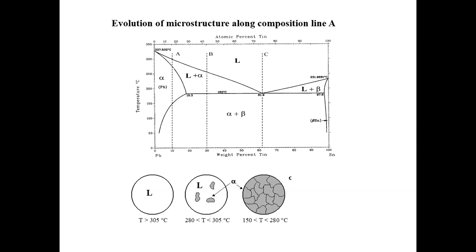Okay. So now before I show the last picture, we know that if I further cool the system, what phase are you going to have if I further cool the system down here? So alpha plus beta. You're going to have alpha plus beta. Does this make sense to everyone? Because I'm now in the two-phase coexistence region. Now, if I just choose this like 100 degrees Celsius, give me a rough estimate. What are going to be the corresponding equilibrium compositions of alpha phase and beta phase? Approximately those. Beta will be around 99 and alpha will be less than 10.